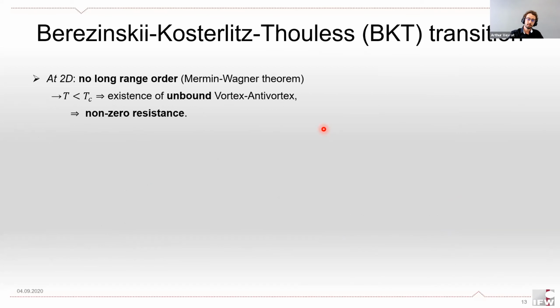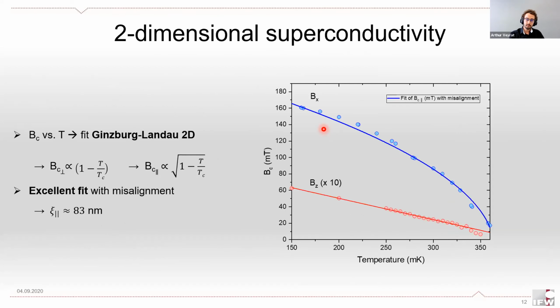Okay. You said that you have this 2D superconductivity in thick samples. Yes. Did you try to control somehow the thickness of the samples and see how this evolves? We have done a study with a slightly thicker sample, a few dozen nanometers thicker, and we do not see this sort of direct hallmark of 2D superconductivity, with very different perpendicular and planar superconductivities. We haven't been able yet to reproduce this study in thinner samples. We're currently starting the measurements, but this is what we expect to see for even thinner samples.